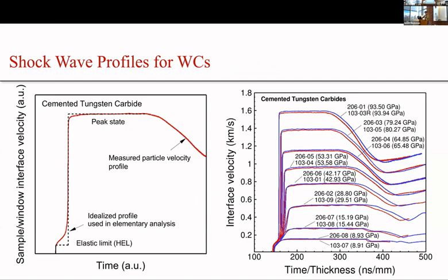The recorded shock wave profile is shown as the red curve in the figure on the left, where we can see there are three different stages. The first stage, if you can see the cursor, is the elastic wave, which is represented by this small jump. The amplitude of this jump is referred to as the Hugoniot elastic limit, or just the HEL. After the HEL, there is an elastic-plastic hardening ramp. And then finally there is the plastic wave, which is represented by a very large jump.